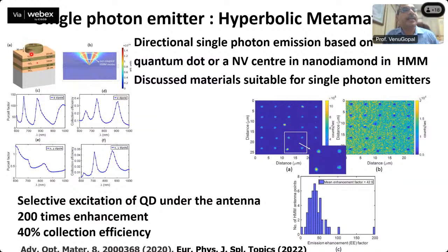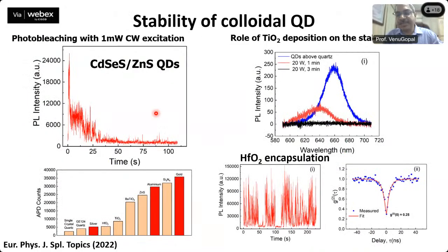So what we did is put an antenna on top. The antenna is designed such that, in a confocal microscope, we have a home-built confocal microscope, so we know the numerical aperture of the lens and all that. Based on that, we designed this antenna so that we collect most of the light emitted from this particular structure. We designed it for emission at, say, 15 degrees and collected photons coming out of them, and then tested it with a nanodiamond with a single NV, so the possibility of having single quantum dot emission from these structures enhances. So we showed single photon emission. But however, one problem is whether it's a quantum dot or a nanodiamond.